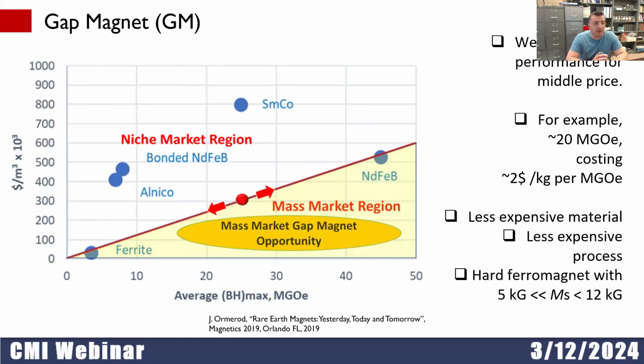So to say, we need a middle performance for the middle price. For example, we need 20 megagauss-oersted performance for $2 per kilogram per megagauss-oersted. We need less expensive material. We need less expensive process. And in fact, it would be okay if we had a hard ferromagnet, so basically with enough magnetic crystalline anisotropy, with magnetization which is between 5 and 12 kilogauss, closer to 12 kilogauss than to 5.